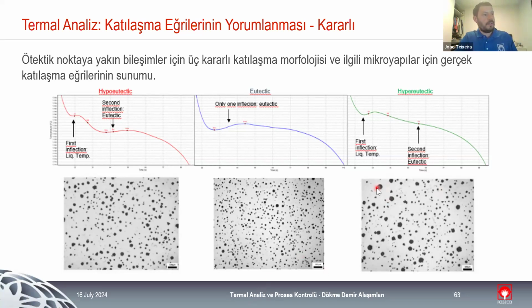And you can see really clearly that for hypereutectic type, we have bigger nodules and smaller nodules. So we have the first phase of graphite being formed really early on, the big ones, and the second phase at eutectic, the smaller ones. For the eutectic, we have a more uniform distribution of the sizes of the graphite nodules, and the same thing for hypoeutectic.